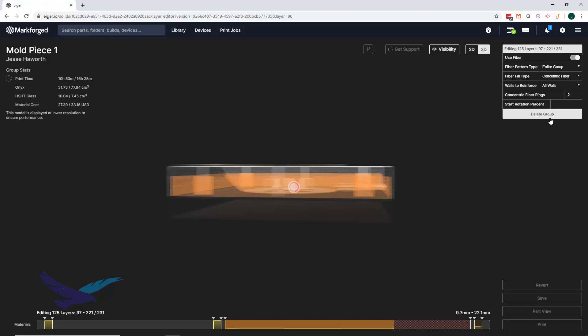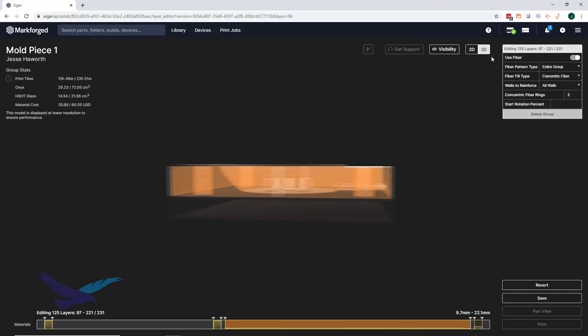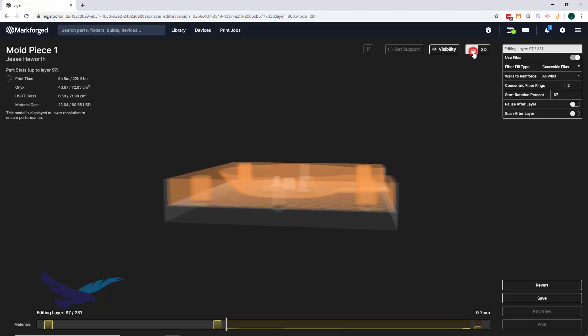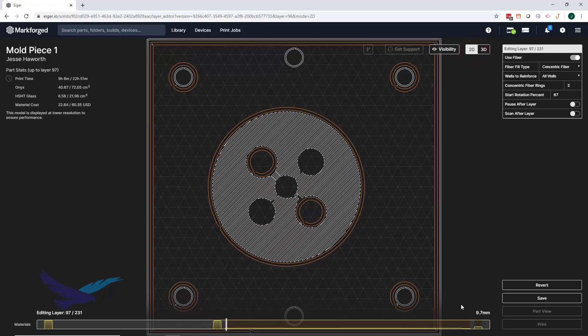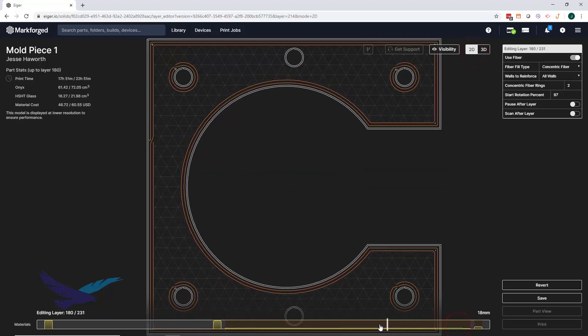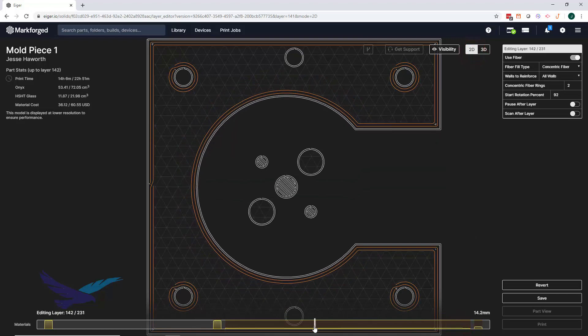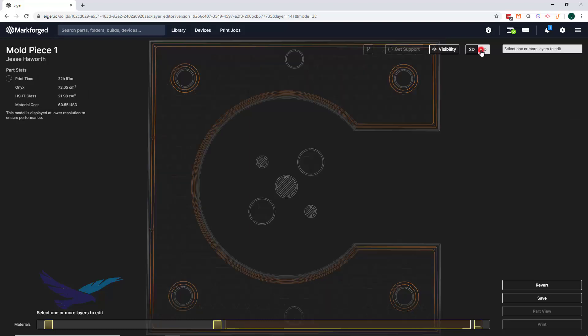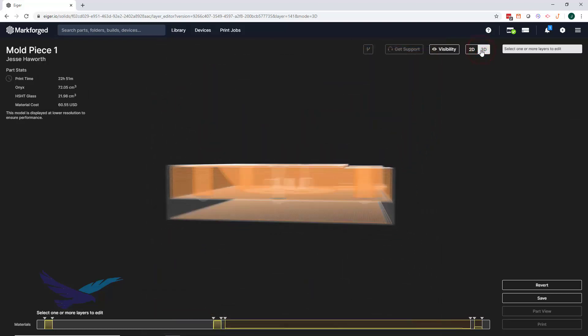After a group of fiber layers is created, it can be a good workflow to use the 2D view mode to inspect the fiber placement. In this case, we can see that some of our holes were not reinforced due to the space required for our two fiber strands. We could use this information to adjust our fiber settings as needed, but since this is just an example, we'll proceed for now.